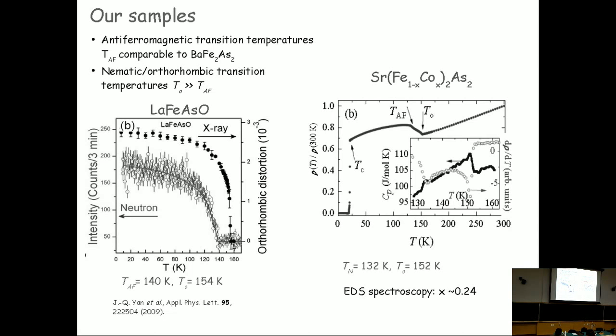And another sample that we studied, we also wanted to study a material belonging to the 1-2-2 family, which as I mentioned to you, was more studied, but we have a stronger doping here so that we could identify, in this case, 3 transition temperatures. This is a resistivity curve.